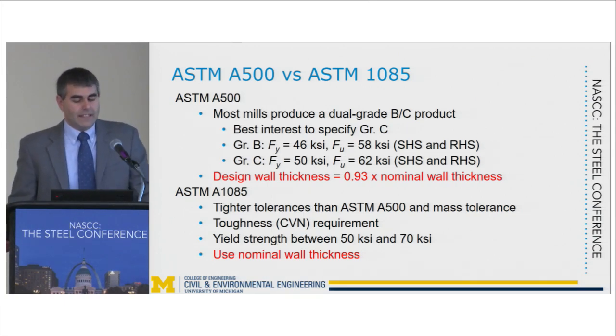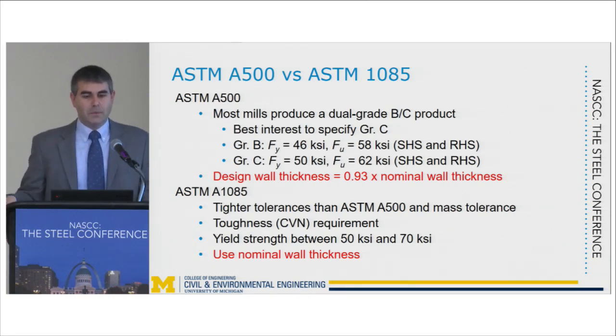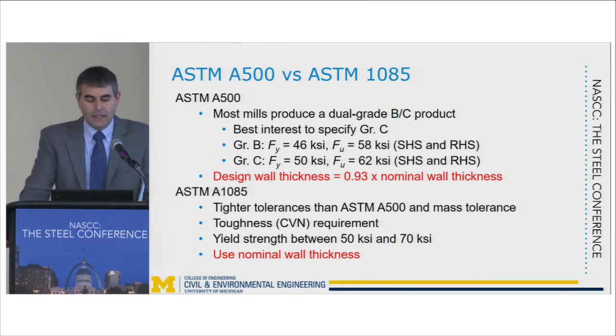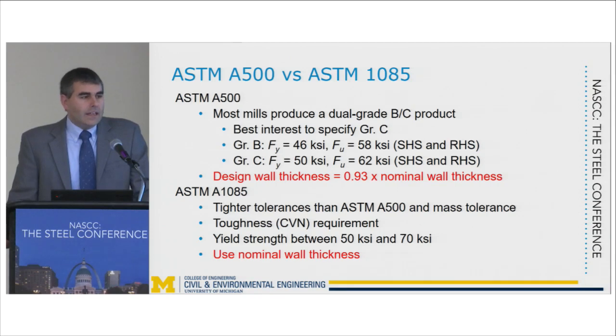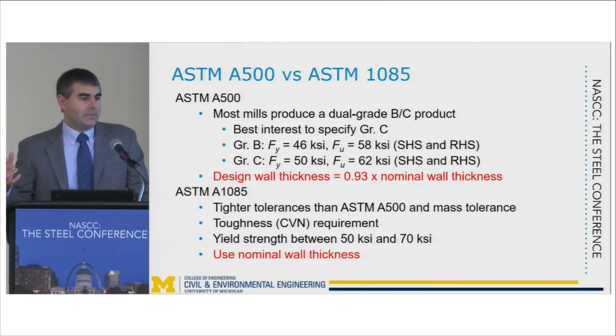But also keep in mind that if you're dealing with an A500 hollow structural section, your design wall thickness, you need to take that as 0.93 times the nominal wall thickness because of the plus or minus 10% tolerance on the dimension. Now, you could go ASTM A1085. This has tighter tolerances than the ASTM A500 and also has a mass tolerance, has toughness requirements, and it requires your yield strength to be between 50 and 70 KSI.